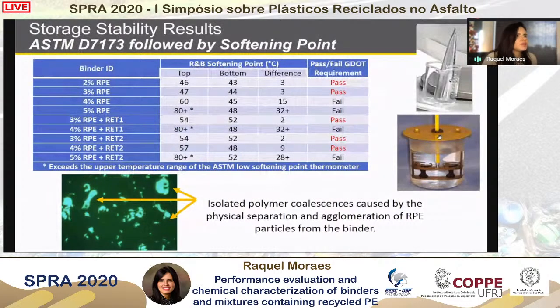So let's go now to the discussion of the results. First, as mentioned before, our initial point was the storage stability test. Even though we know that this test is empirical, it is a very good initial test to screen among different modified binders, since we can clearly detect phase separation. So for these results here, we can see that we have the base binder modified with recycled plastic.